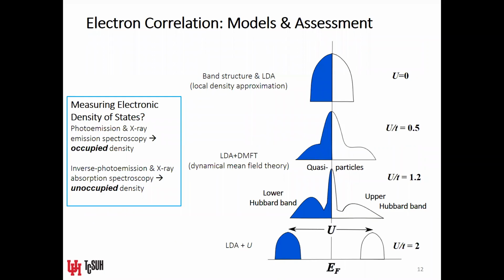So I need to say something about models of electron correlation, because you'll see this. So I've been saying that the iron oxychalcogenides are Mott insulators, okay? And I've been talking about electron correlation. Let me say a few things, give a few more details. So the band structure theory, okay, for example, and models like local density approximation, they work, and if you think of a simple metal, they work well in describing those metals. And in that regime, the metallic state, there is no electron correlation in the band structure model. So the Coulombic energy U would be 0.